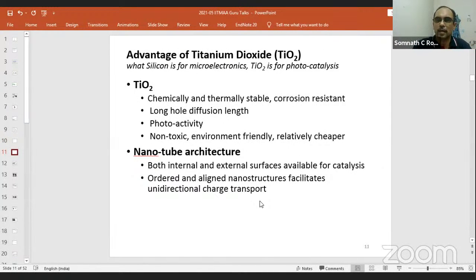The first topic, as I said, is titanium dioxide. Titanium oxide, or titanium dioxide, TiO2, is around us everywhere. You believe it or not, it's around us. We use talcum powder, I have this paint on the wall around me, and in sunscreen pastes or lotions everywhere, there will be a significant amount of titanium dioxide. Titanium dioxide is a white, powder-type material. The advantage is that it is chemically and thermally stable, with corrosion resistance. I'm not going through the technical jargon here, such as long hole diffusion length, but it has a very good property of sunlight absorption. Now, coming to that, we are particularly interested in, as I said, one-dimensional.